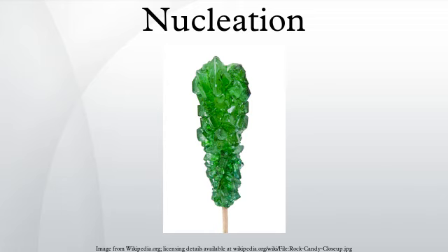For nucleation of a new thermodynamic phase, such as the formation of ice in water below 0 C, if the system is not evolving with time and nucleation occurs in one step, then the probability that nucleation has not occurred should undergo exponential decay as seen in radioactive decay. This is seen for example in the nucleation of ice in supercooled small water droplets. The decay rate of the exponential gives the nucleation rate.